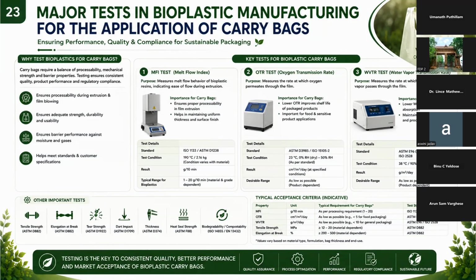So in SIPET Kochi, this MFI testing is available. Next is the OTR test, the oxygen transmission test. It is a major test for thin film plastic testing, and the standard is ASTM D3985. The test conditions are very important, and the humidity value is also important. The temperature and humidity values will have a major impact on the result.